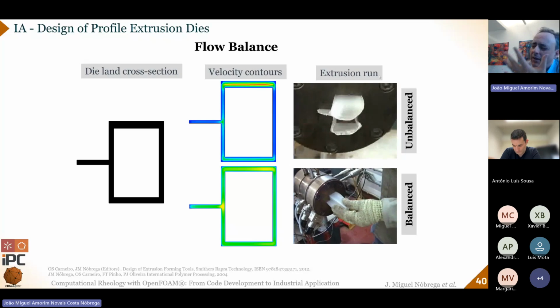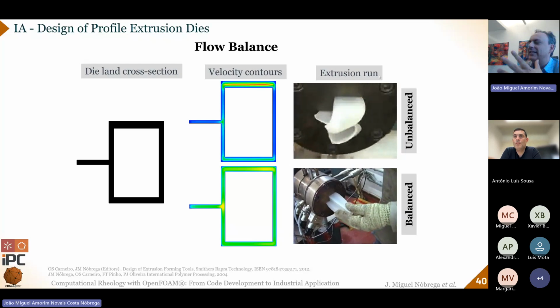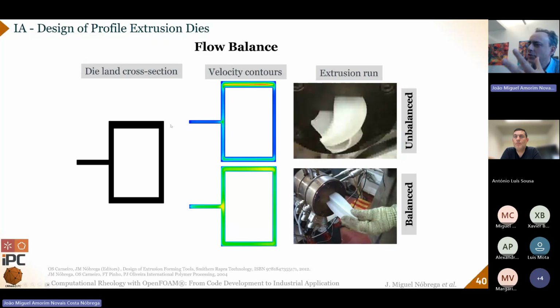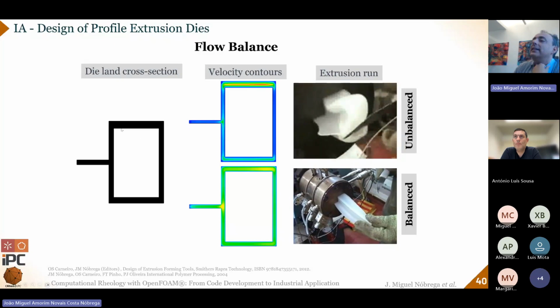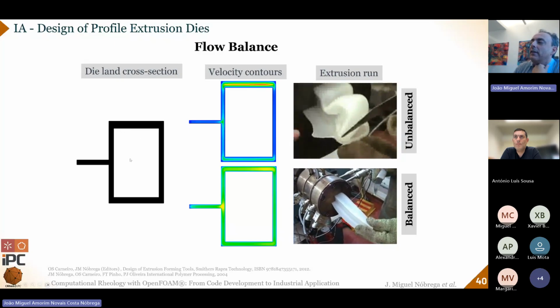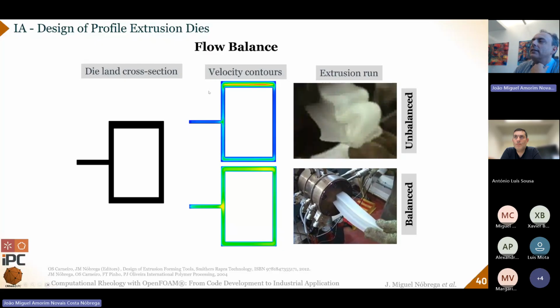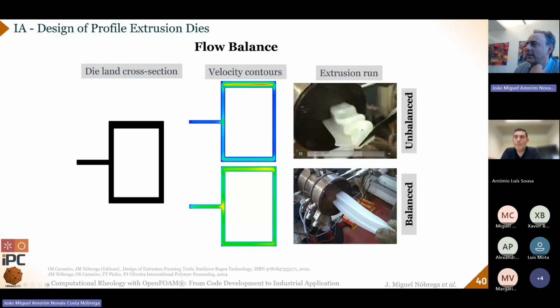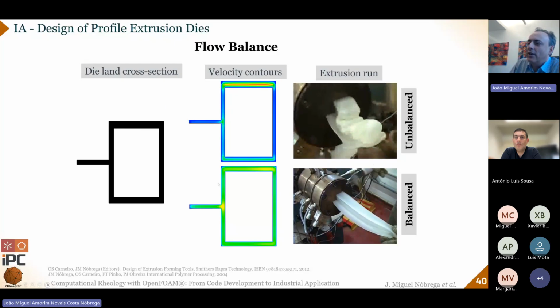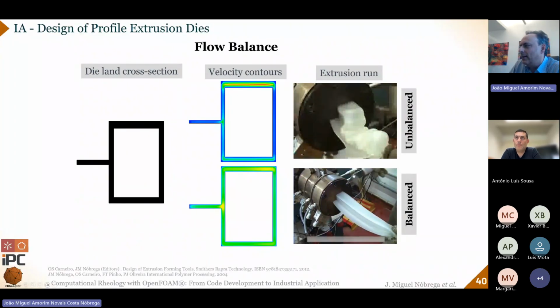One of the difficulties of designing profile extrusion dies is flow balancing, because most profiles have different thicknesses, and if no care is taken, the material does not distribute properly, as you can see in this movie, so it cannot produce the actual profile. In order to obtain the profile you need to balance the flow, and this is an example of a balanced flow of the same tool. This is the exact same tool, same geometry, but with different flow channel geometries.